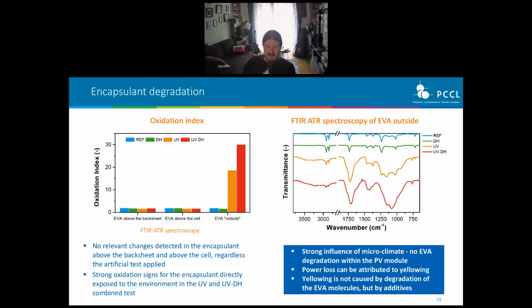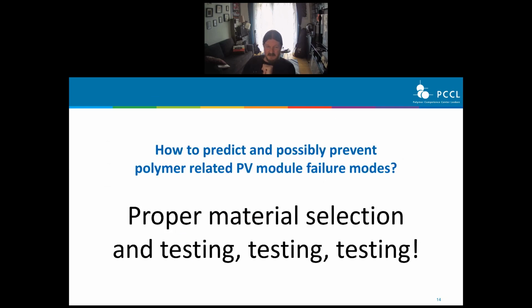The power loss that we found was attributed to yellowing of the encapsulant, and even though we saw yellowing after each test, only after UV tests was this correlated to a power loss, because we found two different mechanisms of yellowing in the PV module.